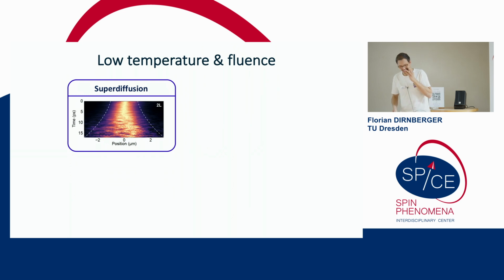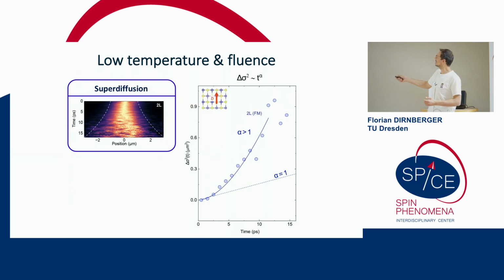So one thing is that when we look at the transport of these excitons in a bilayer sample, and this is very specific for a two-layer chromium sulfide bromide crystal, instead of a regular, more or less diffusive expansion of the mean squared width of this distribution, we see what we call a superdiffusion. This is just what it's called when the width of a distribution of particles increases superlinearly in time. So you can see here this clear behavior that deviates from a linear increase in time.